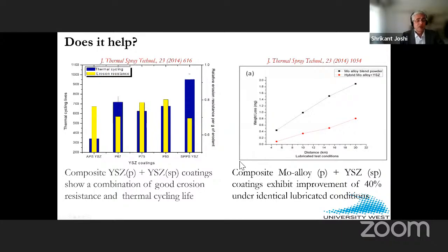Here is an example where we had used yttria stabilized powder and the right kind of solution precursor to also form yttria stabilized zirconia, right? And that serves to toughen this in a way. So we found these coatings to be ideal when you wanted a combination of thermal cycling lifetime extension and good erosion resistance, for example. And we have also done this for a couple of other systems at that time.